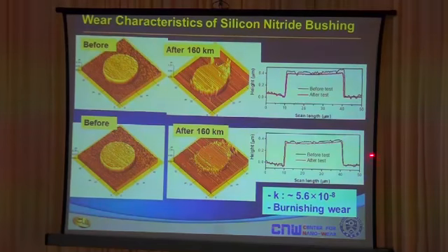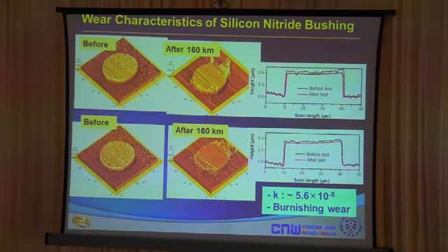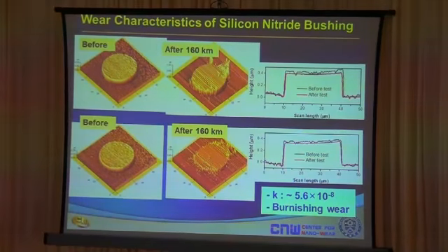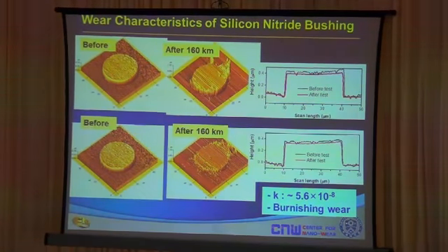What if we move on to a much harder silicon nitride bushing? Silicon nitride bushing, you can see that wore out very little, and the wear coefficient in this case was in the range of 10 to the minus 8, which was much lower than that of the silicon bushing itself. So what is all this showing us?